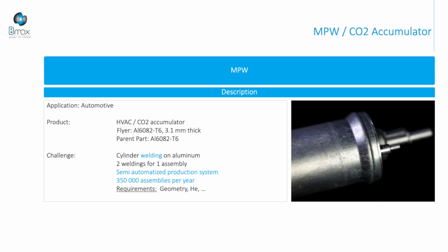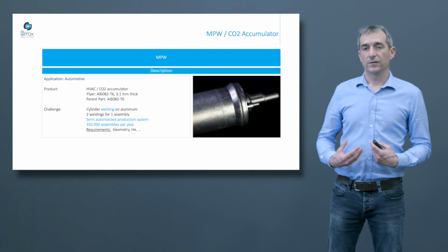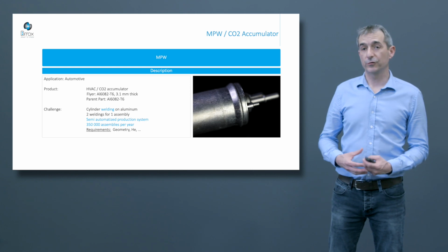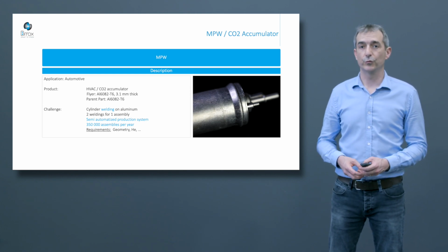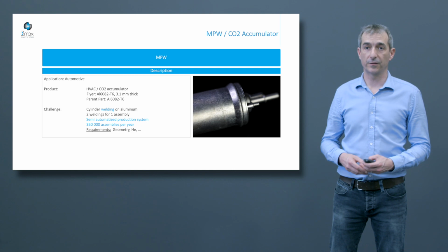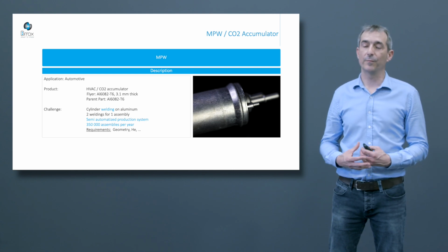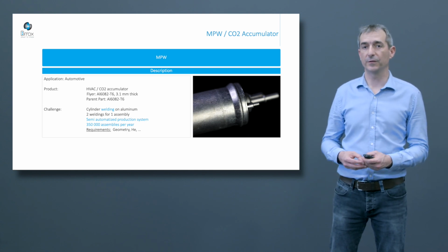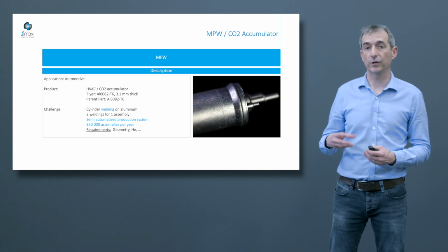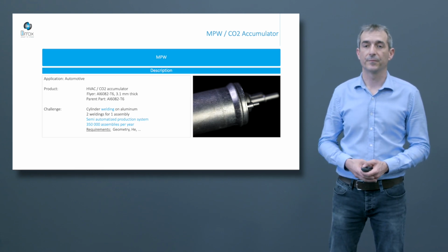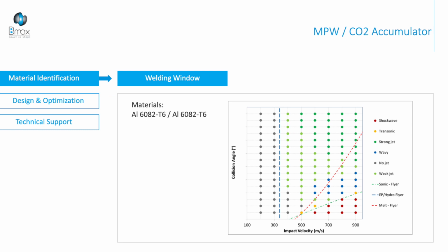The aluminium is 6082 temper T6, and the flyer has a thickness of 3.1 millimeters. The project consists of designing a semi-automatized production system able to produce 350,000 assemblies per year. The requirements are about geometry, helium leakage, and there are specific functional requirements about cycling. First of all, we define the welding windows for this aluminium 6082 T6 on itself, numerically and theoretically.